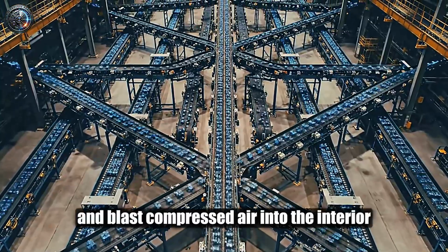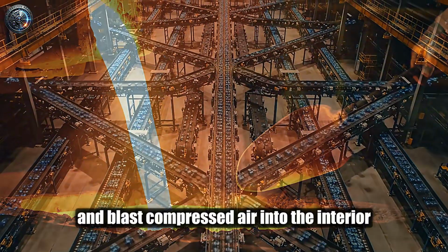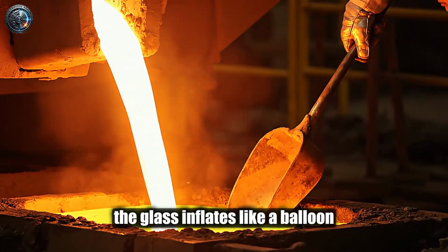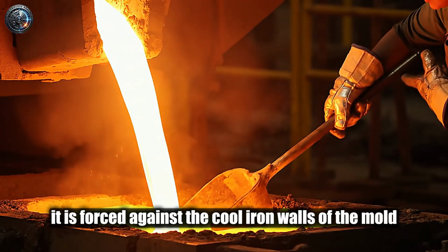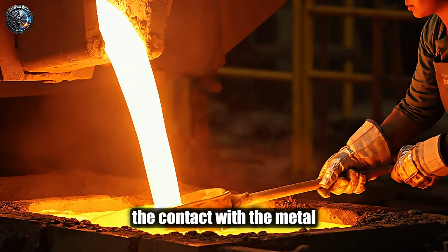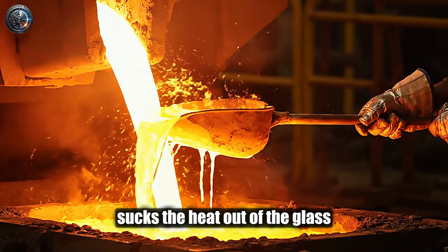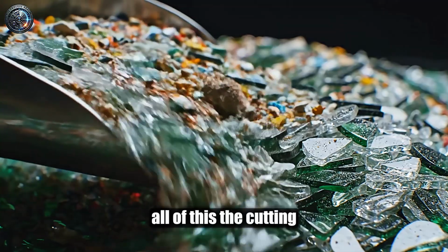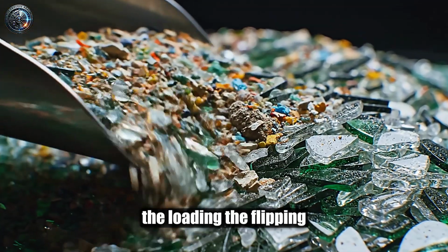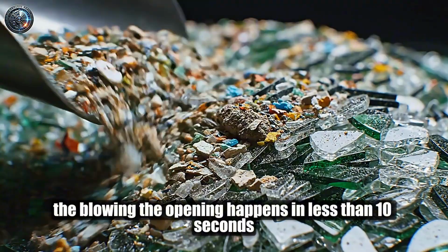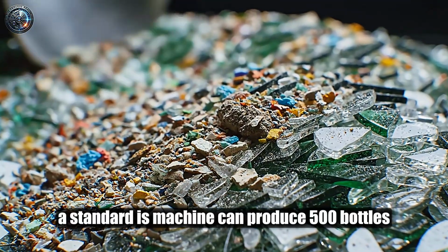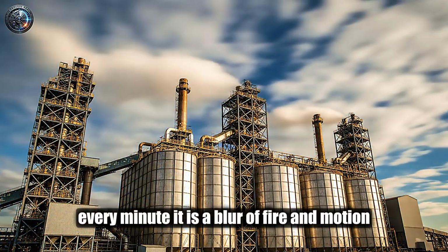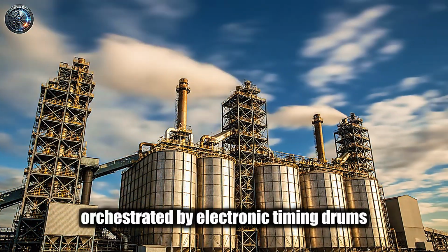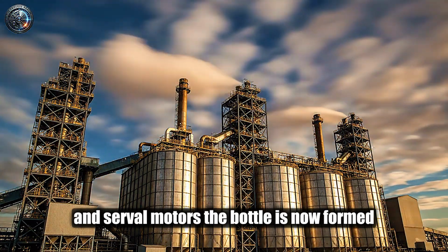A blowhead descends and blasts compressed air into the interior. The glass inflates like a balloon. It is forced against the cool iron walls. The contact with the metal sucks the heat out of the glass instantly, freezing it into its final shape. All of this, the cutting, the loading, the flipping, the blowing, the opening, happens in less than 10 seconds. A standard IS machine can produce 500 bottles every minute. It is a blur of fire and motion, orchestrated by electronic timing drums and servo motors.